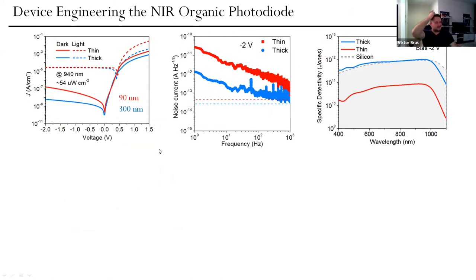And we made different types of devices, with 90 nanometers and 300 nanometers thickness of the active layer. We see that the reverse dark current, which is not good in devices made as photodiodes, is lower for a thicker active layer. A thicker active layer provides options to reduce non-uniformity in the field, some pinholes, and reduces the current which flows through the active layer at reverse bias. When we also measured noise current, we see that within the spectral range of electrical noise, it is significantly lower than for the thin device.